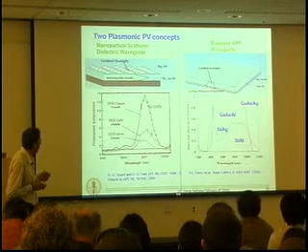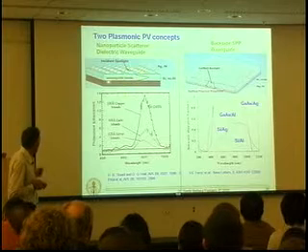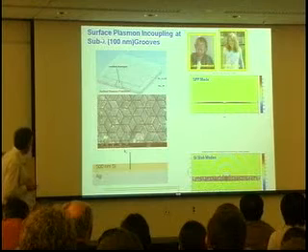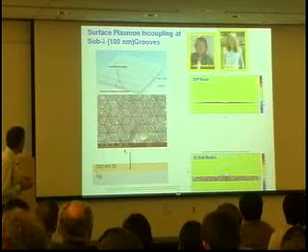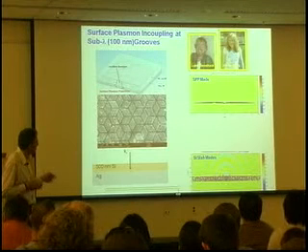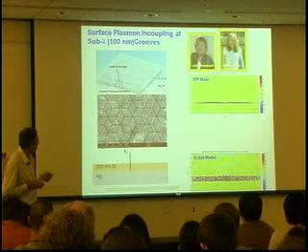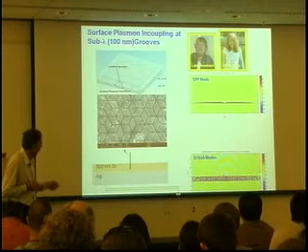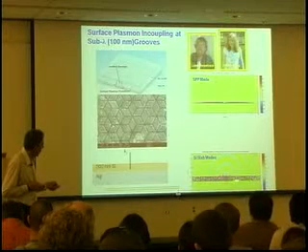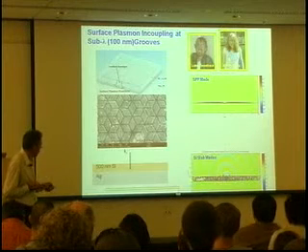And in both cases, we can generate guided modes here that have substantially increased absorption relative to single-pass absorption through a thin sheet. This is an example of just showing a model system of a textured reflector. And this is a modal decomposition in simulation showing the confinement of the surface plasmon polariton mode in a thin film. And this is the silicon photonic, this is several TE optical modes in the same thin silicon film, about half a micron thick.